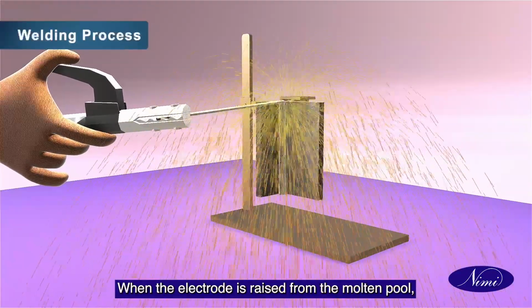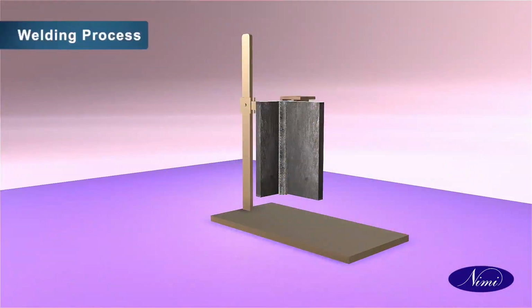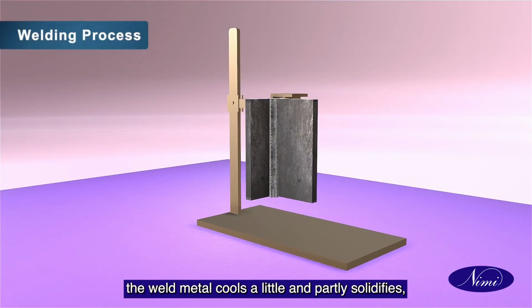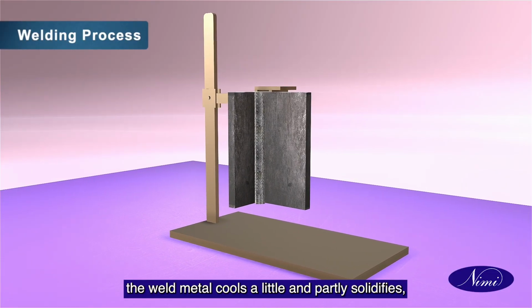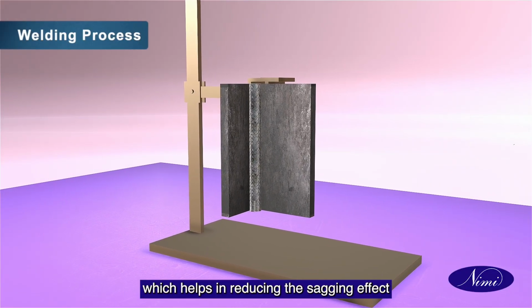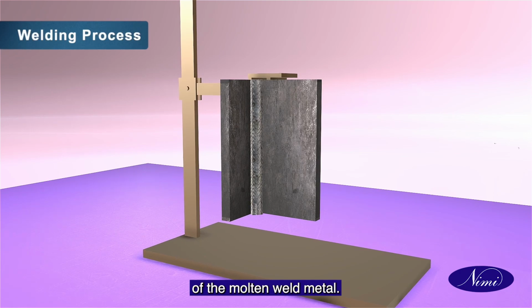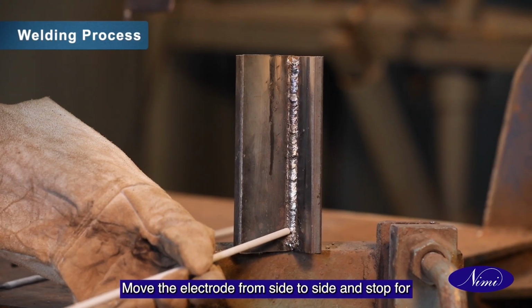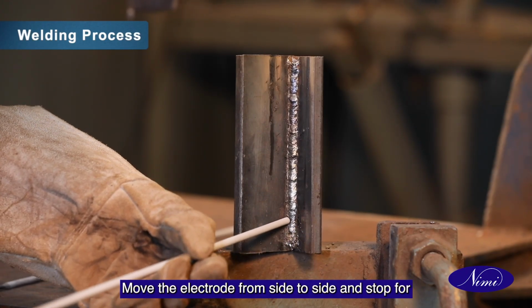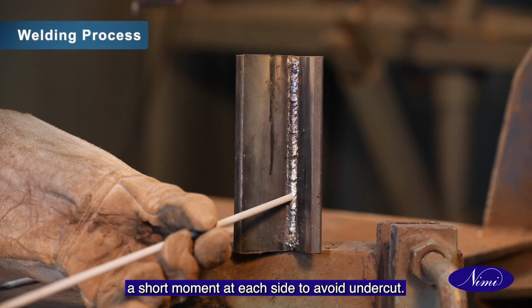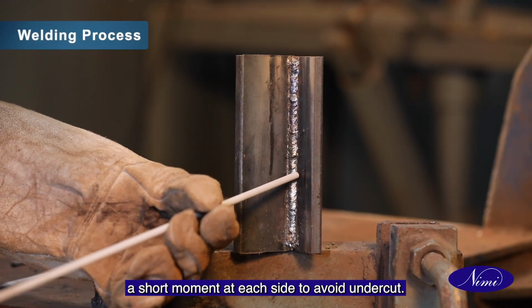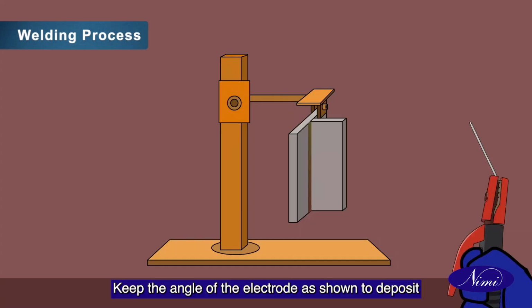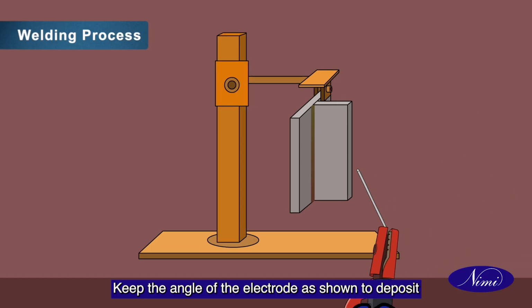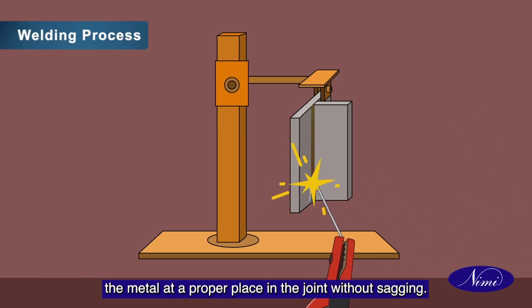When the electrode is raised from the molten pool, the weld metal cools a little and partly solidifies, which helps in reducing the sagging effect of the molten weld metal. Move the electrode from side to side and stop for a short moment at each side to avoid undercut. Keep the angle of the electrode as shown to deposit the metal at a proper place in the joint without sagging.